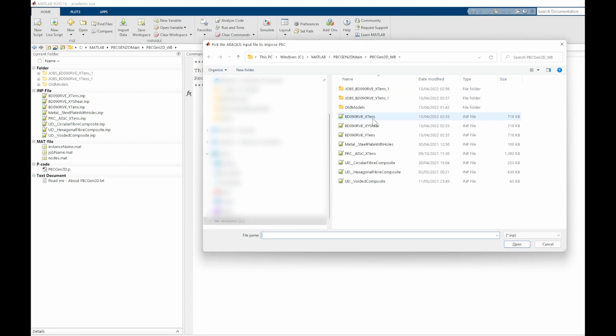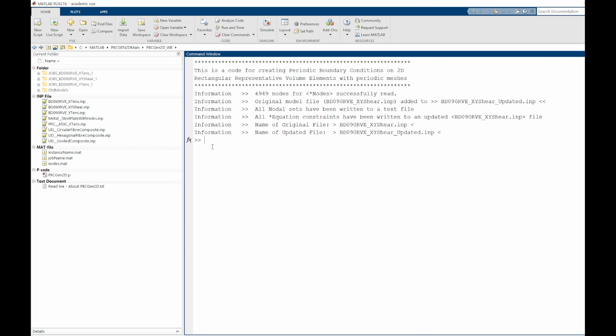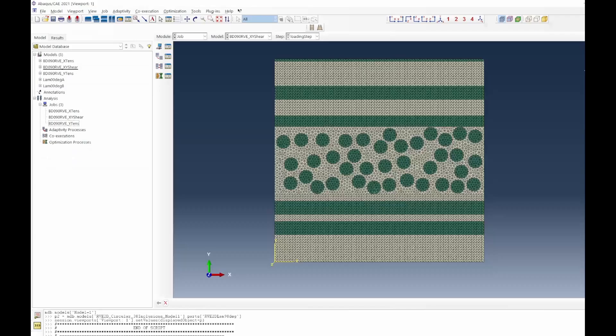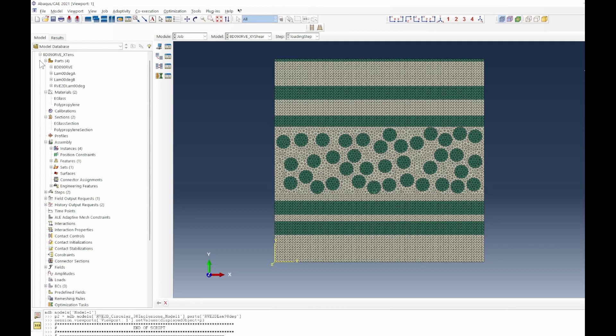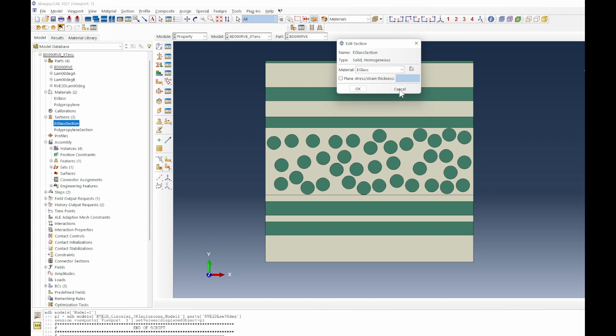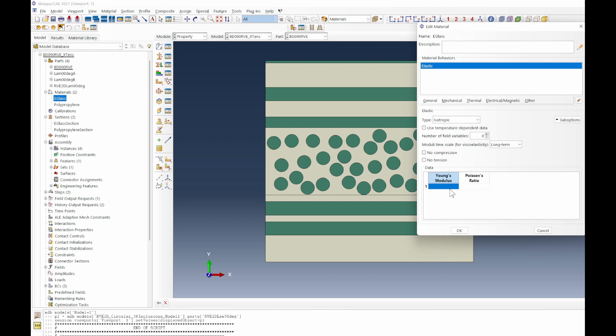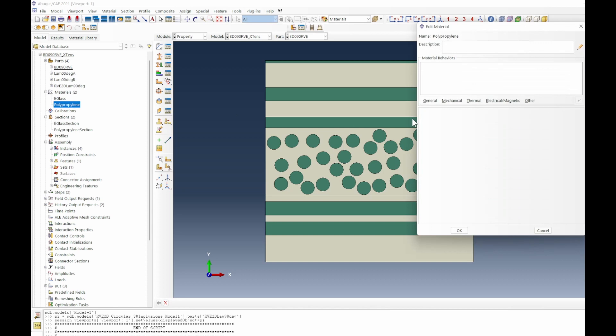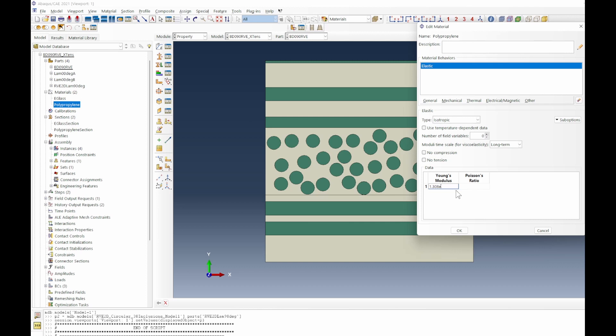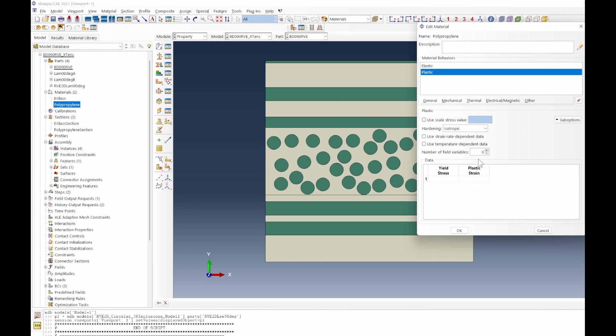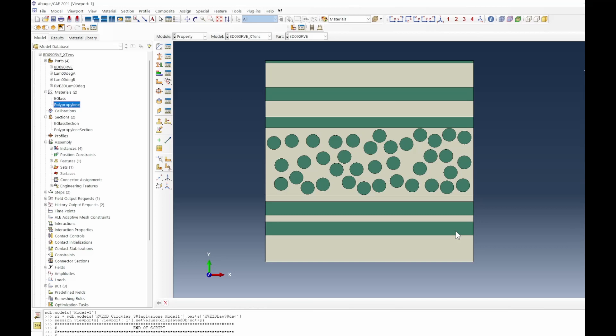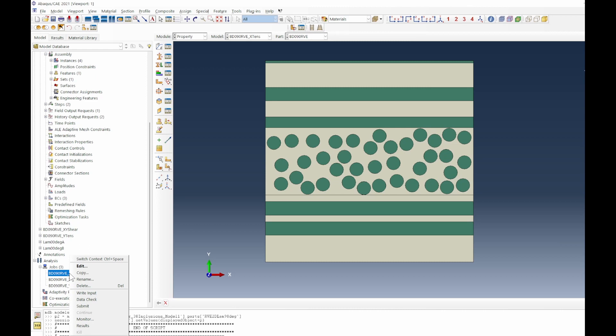We are done with PBC application. But before running, we realize we didn't specify material properties. Going back to Abaqus models: E-glass properties are Young's modulus = 73 GPa and Poisson's ratio = 0.2. Polypropylene properties are Young's modulus = 1.308 GPa and Poisson's ratio = 0.4 for elastic properties. We then write and submit the updated input file for the X-tensile case.